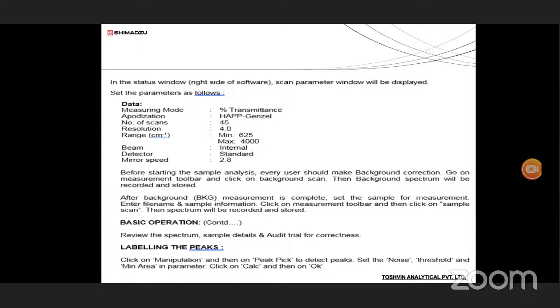Then for apodization, we select Happ-Genzel. Apodization is a window for collecting the spectra in a specific region. The number of scans we mention is 45 by default. If you want to reduce noise, increase the number of scans, and the noise will automatically be reduced. We recommend a number of scans of more than 60. With more than 60, multiple scanning increases and the background noise is reduced. So 45 is the default, but we recommend taking more than 45, up to 100, no issue.